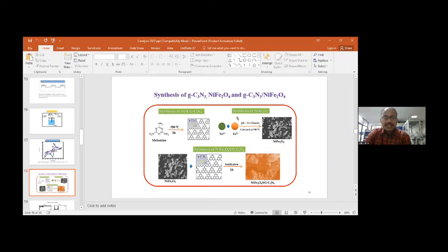In this direction, we have synthesized materials in the present study: graphitic carbon nitride, nickel ferrite nanoparticles, as well as graphitic carbon nitride functionalized with nickel ferrite nanoparticles. We prepared the graphitic carbon nitride using melamine. Then we used nickel and iron sources, maintained the pH, and added glucose as a fuel. A combustion method was carried out, then calcined at 500 degrees Celsius, and we obtained the nickel ferrite. Once we had the nickel ferrite, we put it into a simple ultrasonication method with the graphitic carbon nitride, sonicated for 1 hour, and got this modified material. This modified material we drop casted upon the screen printed electrode, not on the glassy carbon electrode.